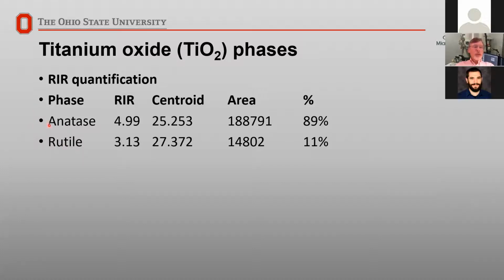So this particular sample, we went through, we did the analysis on it, and then we used some library sensitivity values, and we could then quantify the results. So this was almost 90% anatase, 11% rutile. Now these have the same chemical composition, but they have different structures, and we're able to see that difference.